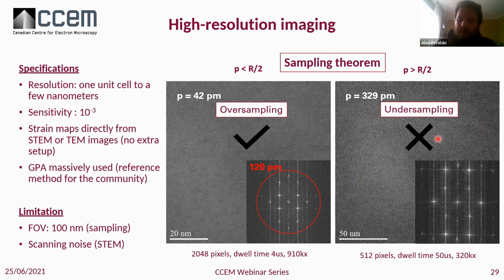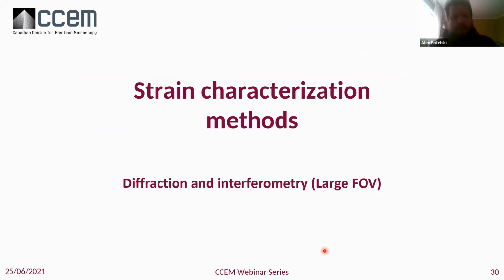And the undersampling will cause some irreversible distortion of your signal that will completely change your geometrical structure, which is not representative of the crystal lattice. So again, keep in mind that when you do this type of high resolution imaging, you can't automatically go to a larger field of view. You will need to find a new strategy to cope with that. So that's for the high resolution imaging.